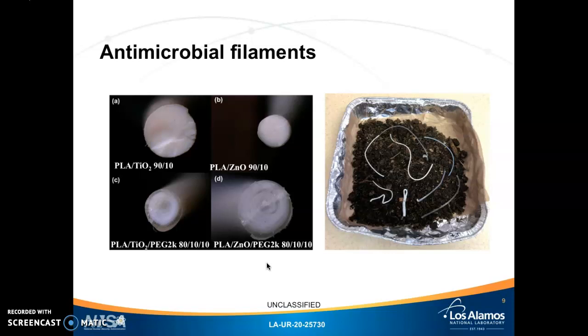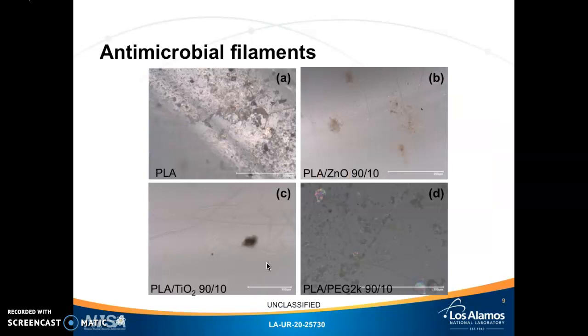To test the antimicrobial activity of the filaments, we placed and covered the specimen in soil for a prolonged period of time at constant humidity and temperature. Some results from this experiment show that while various microorganisms can tear and alter the PLA filaments, they are less successful at thriving on the filaments with ceramic fillers.